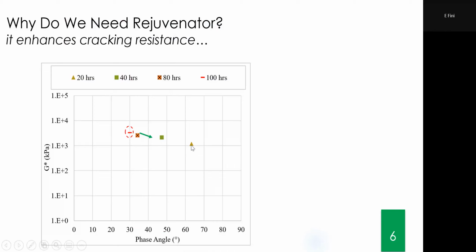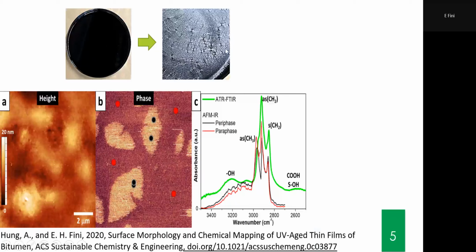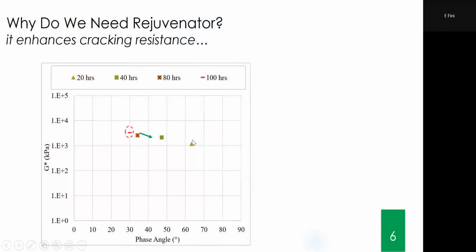It's expected, isn't it? A brand new material, or not even brand new, this is 20 hours. So 20 hours and then 40 hours, then 80, and then the one in the dashed line is 100. It's expected because the material becomes more brittle, more stiff as you age it. Just looking at this picture, you get that same feeling, isn't it? So this becomes more stiff than this. So if I'm going to shear it, this will shear easier than this, and that's what this test said. So aging makes it go to a higher modulus.